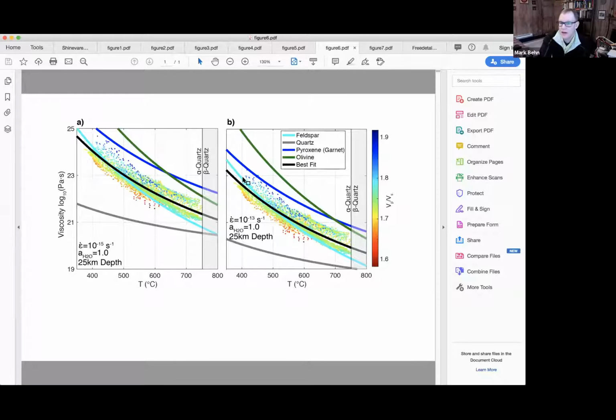So it may be that in certain areas, you can actually start to move towards still using a single flow law. Now, what you can see is that the viscosities are dominantly affected by temperature here, but at the same time, there is variability by at least one full order of magnitude around that. So there can be local variability potentially due to the development of fabric or variations in the chemistry of the rock that then generates variability in the mineral phases that are present. Or even the presence of melt, which is not shown here. That would be in addition to any variations we saw here.